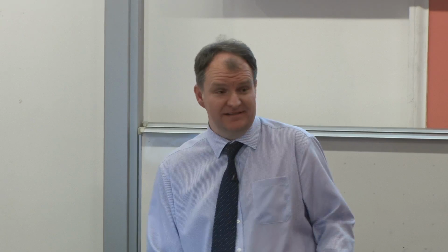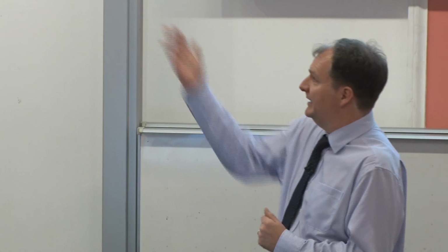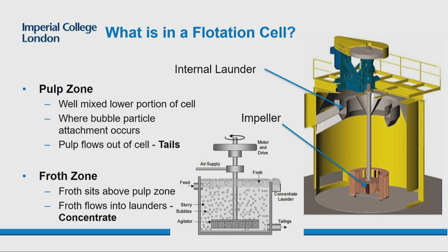The flotation process itself occurs conventionally in a flotation cell, and these flotation cells have two parts to them. They have the bottom section, which is mixed. You have an impeller at the bottom, a very rapidly spinning impeller, and it's along the shaft of that impeller that you're introducing the air. So the air comes down that shaft, gets broken up into fine bubbles in the impeller, or between the impeller and stator. And then you have a relatively well-mixed zone at the bottom, which is where all the particles you want end up becoming attached to the surface of these bubbles.